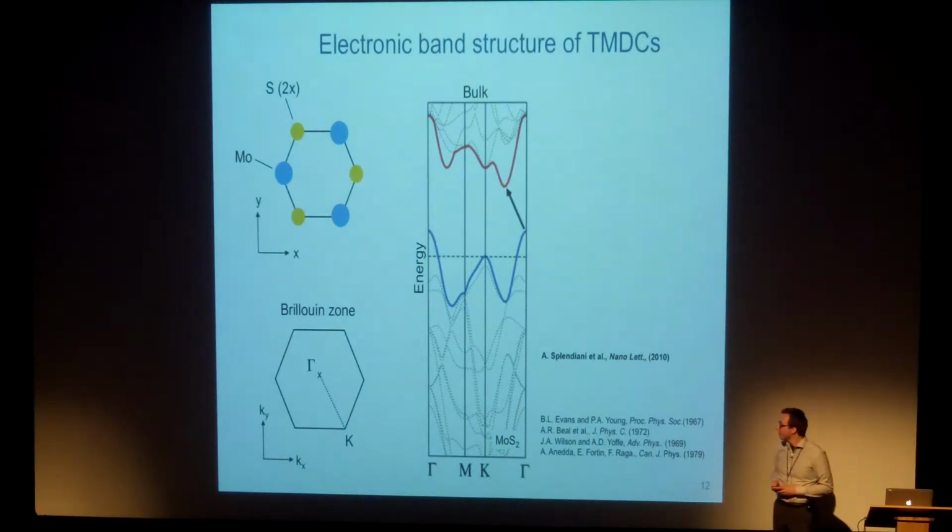the momentum. Now, if we decrease the thickness of these layers, we can think about it in terms of quantum confinement effect. So basically, the electronic levels will move depending on their mass in the z direction. And since the mass is not constant and is different for different values, different positions in the Brillouin zone, the bands will move differently. And what happens is the following.